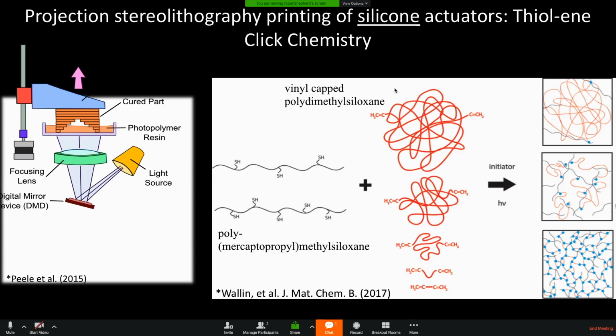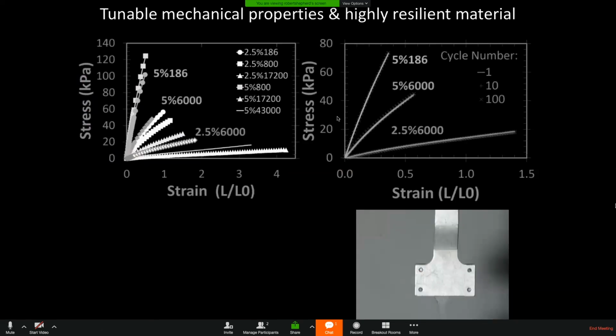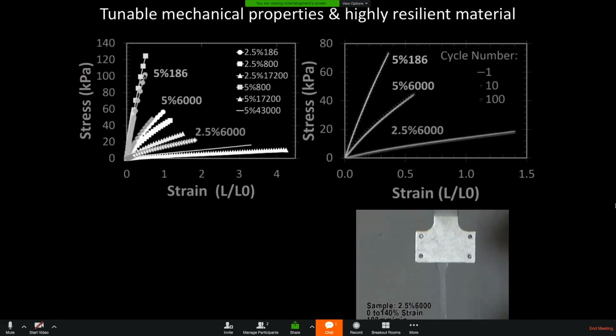So we came up with a thiol-ene silicone click chemistry to print these silicones directly that have, again, very low elastic moduli. And we can tune this using the density of thiol groups and the molecular weight. So the density is represented by this 5%. 5% of the groups are cross-linked using thiol-ene click reaction. And then this 186, 6,000, these represent the molecular weights of the polymers. And the bigger this number is, the softer it is, and the more it can stretch. And the other side of it, the higher the percentage is, the less it can stretch and the harder it is. So we have to tune between these things.